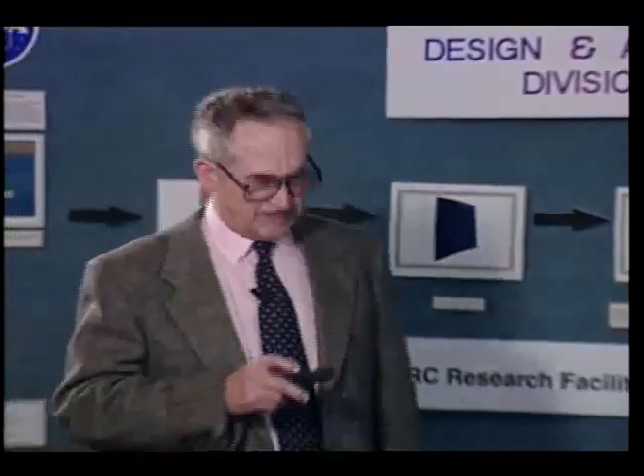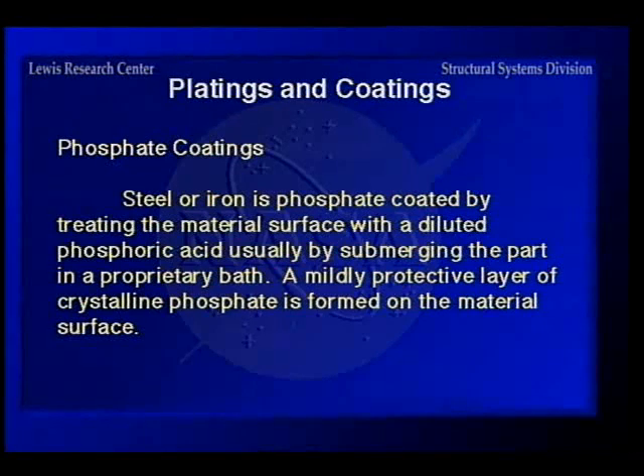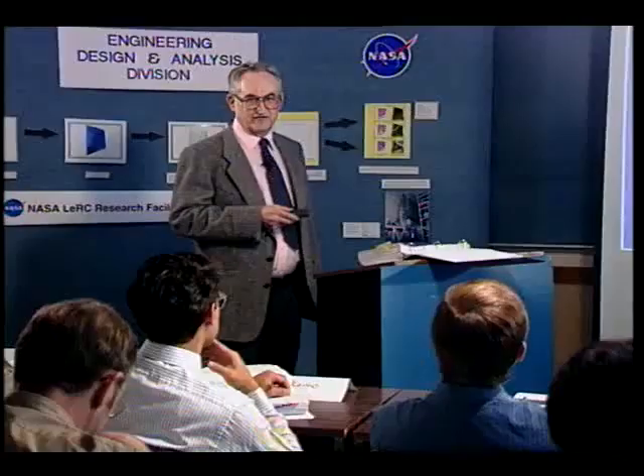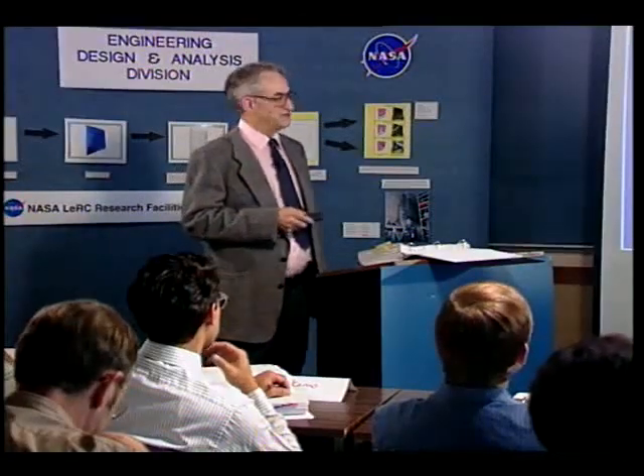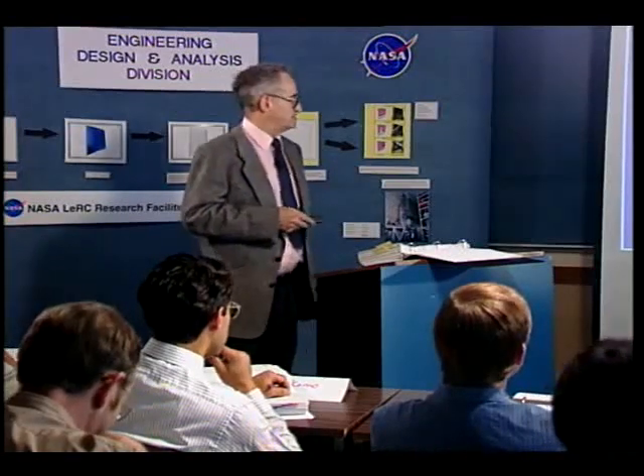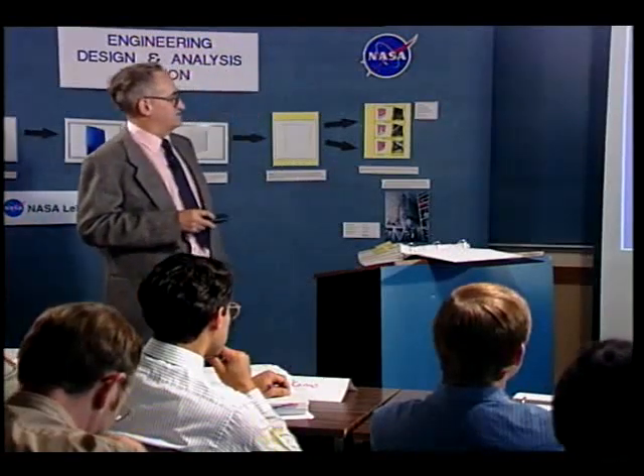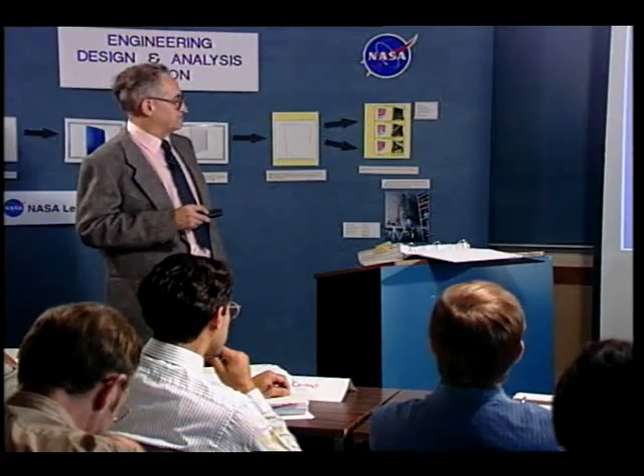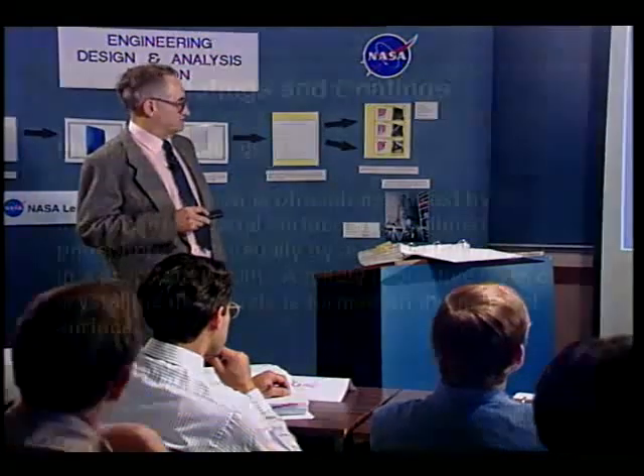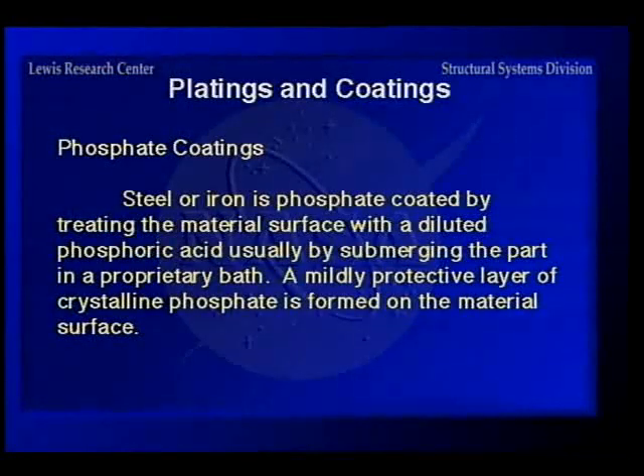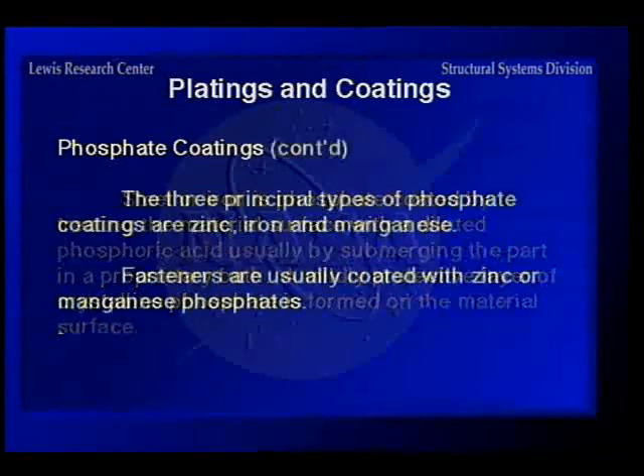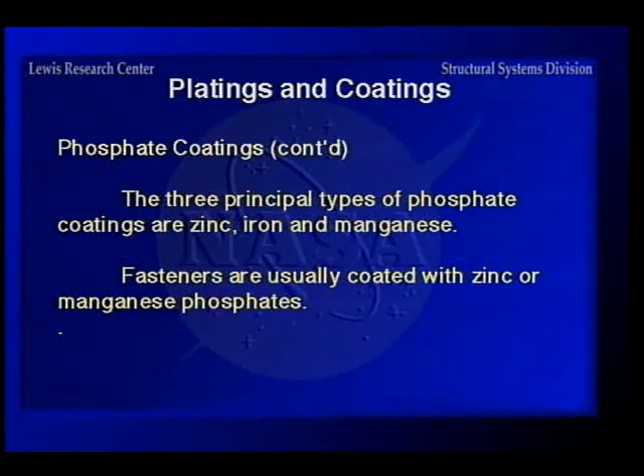Now, the phosphate coatings, this is used a lot in the automotive business because it's cheap. You throw a cup of phosphate in a barrel and put a bunch of fasteners in and shake them a few times, and you have phosphate-coated fasteners, more or less. And so the mildly protective layer of phosphate is formed on the surface, and there's 3 different ones. There's zinc, iron, and manganese, and the ones usually used for fasteners is the zinc or manganese.